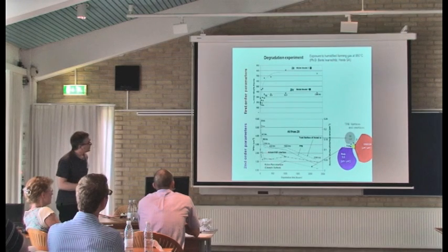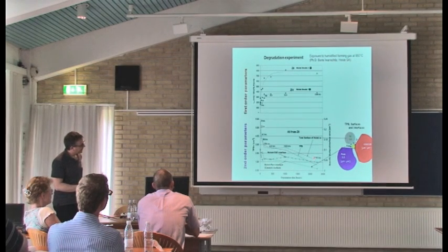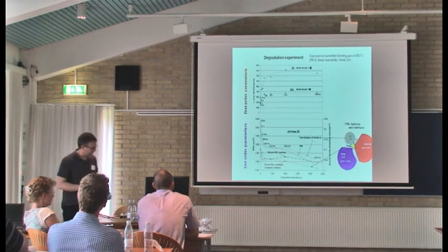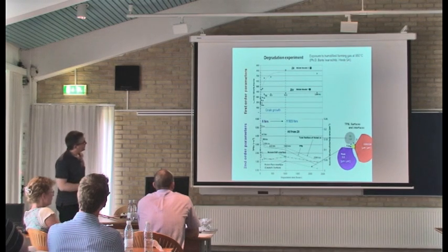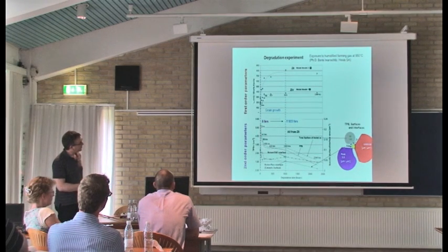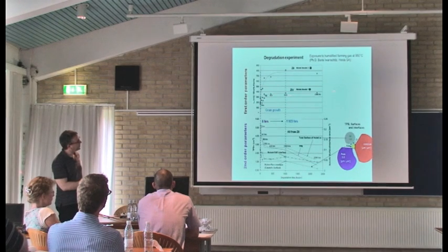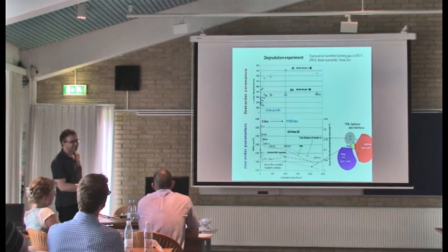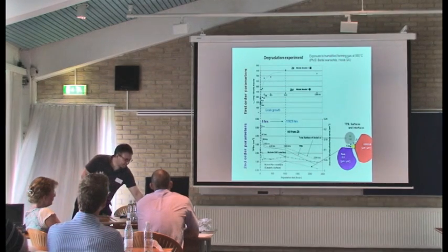TPB, and this line, is strongly correlated again with the surface of nickel, or with the interface of pore and nickel. We also see that TPB and the surfaces are changing during the phase where we have grain growth, but then there is also a change of the TPB which is not related to grain growth.